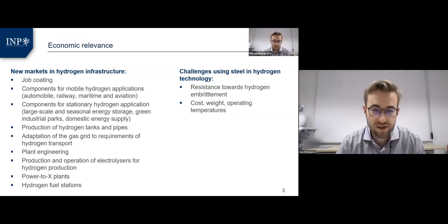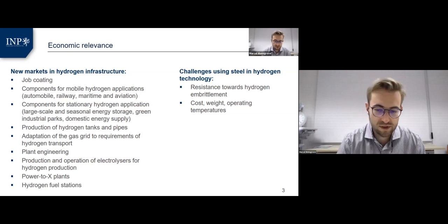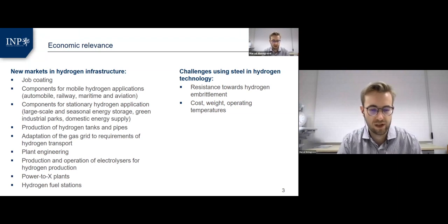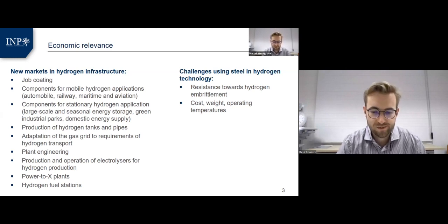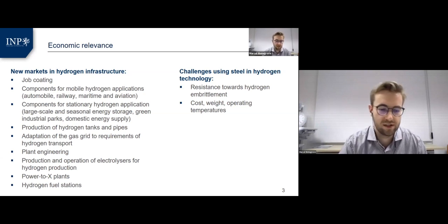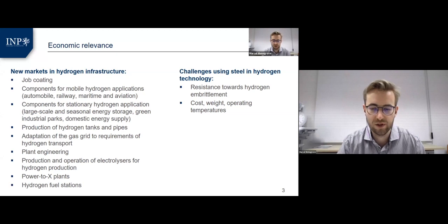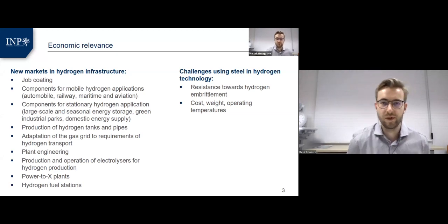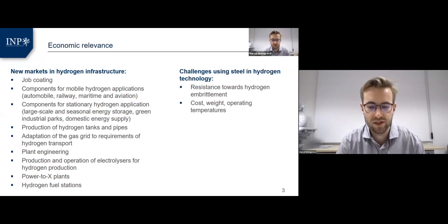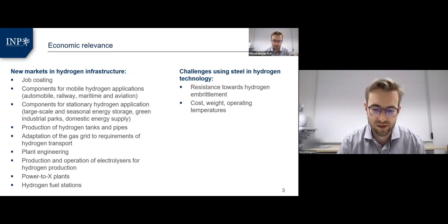And concerning the use of steel in these new sectors, the main challenges are achieving resistance towards hydrogen embrittlement, reducing cost, weight, and achieving suitable operating temperatures. Steel as a construction material shows high toughness, durability, and resistance to external influences, as well as excellent recyclability. On the other hand, especially in dynamic operation, these steels are often exposed to large pressure fluctuations, up to 900 bars in the automotive sector, and these pressure changes, which are associated with corresponding mechanical loads, promote hydrogen embrittlement.